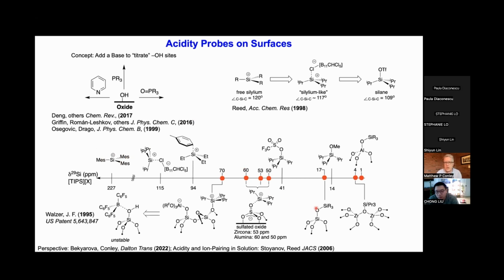So when we started at UCR, the examples of silanes on surfaces were all over here. So silica capped with silyl groups is shielded. Alumina capped with silyl groups is shielded. So these are essentially strongly coordinating anions, if you want to think about it in a purely heterolytic sense. The sulfated oxides that I just showed, that behave as mild acids but coordinate to transition metals to form ion pairs, when you react with silane reagents, you actually end up in a more deshielded regime than you have for TIPS triflate. And I'll show later that these actually behave like sililium ions, so we're across that sililium-like threshold.